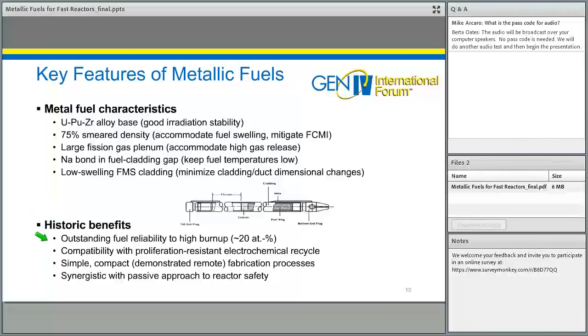Now, this technology has some historic benefits. Like I said, once the lower smear density approach was undertaken, metallic fuels have proven to be capable of operating reliably to very high burnups. EBR-II driver fuel was approved to 10% burnup and never experienced failures to that burnup level. Experimental fuels and experimental subassemblies went to much higher burnups, 20% or even above.